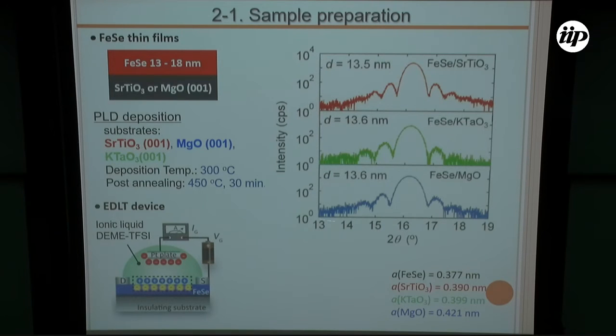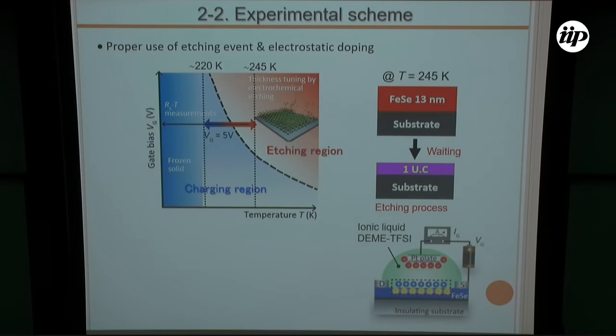And also from these fringes, we can estimate the thickness very correctly. Using these films, we made EDL devices using the ionic liquid DEME-TFSI. This figure shows our experimental scheme showing the relation between the gate bias voltage and temperature, where the boundary between the blue electrostatic region and the red electrochemical etching region is located like this. After many preliminary experiments, we finally found that at 245 Kelvin with 5 volts, very slow etching starts around here. So we use this temperature for decreasing the thickness.